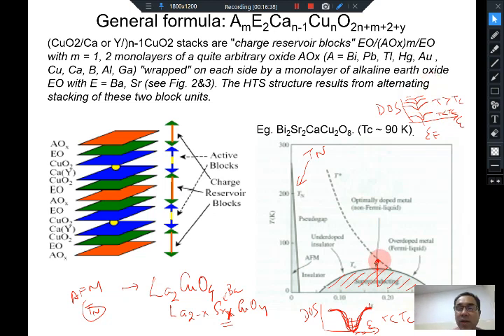So at this value of doping, even if you cross the superconducting transition, one finds that up to a certain temperature window, up to this region, there is a weak gap which is present, and only above this temperature the gap disappears. You can go to a different doping and you will find that this range increases. So even above the superconducting state, very strangely over a certain window, you see something like a gap in the density of states still surviving in these superconductors, and this is called the pseudo gap